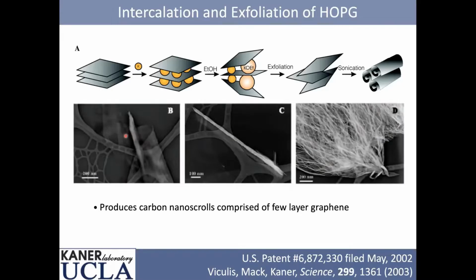Just like I'll show you that if we evacuate the material, we just pull it through a filter, these pieces of graphene just simply stack up. And instead of getting graphite, what you get is graphene paper. So it's just simply, graphene by itself is not stable. Either it finds another sheet of graphene and starts to graphitize, or it finds itself and forms scrolls. Or if you have Scotch tape or some other surface, it will stick to that surface.